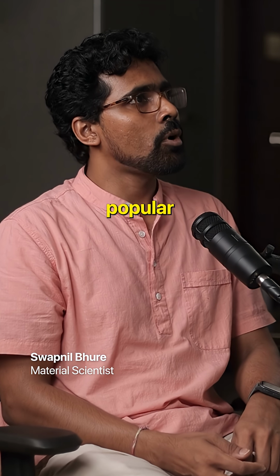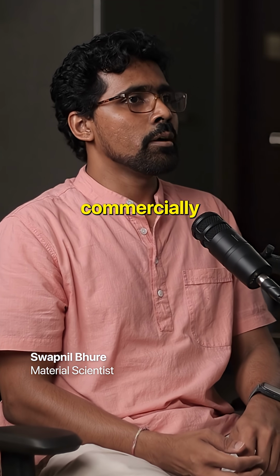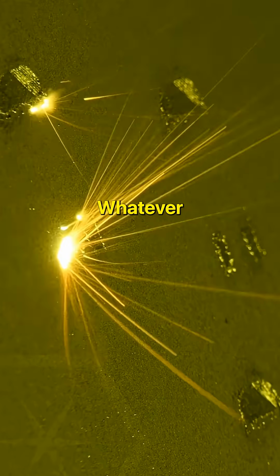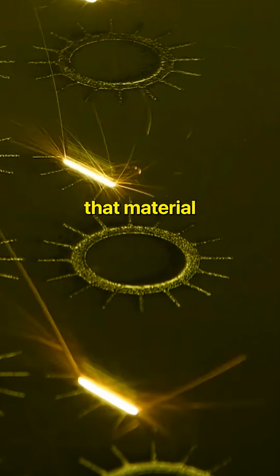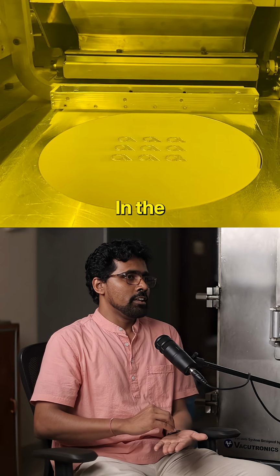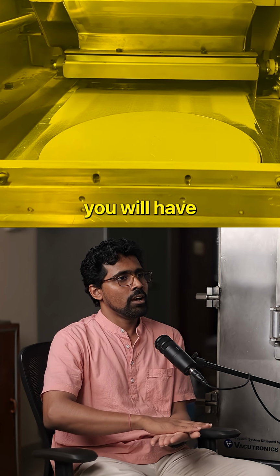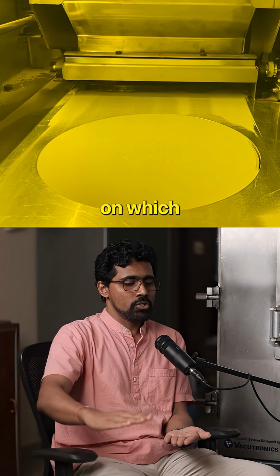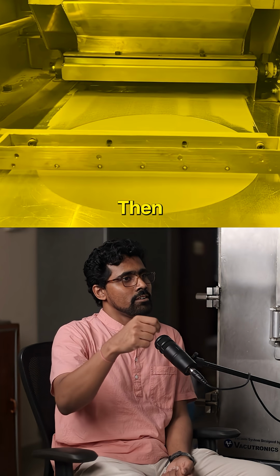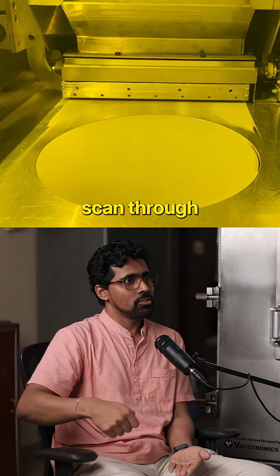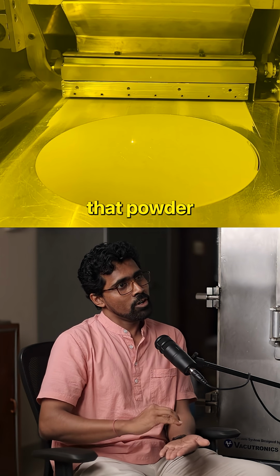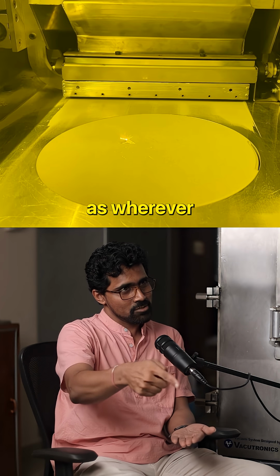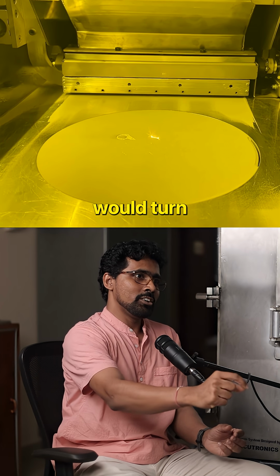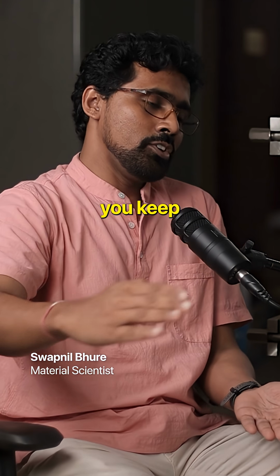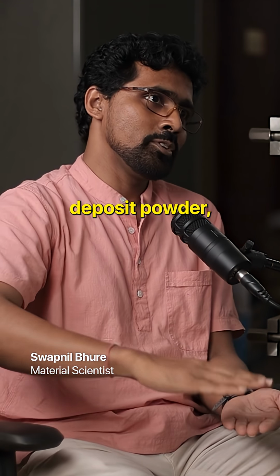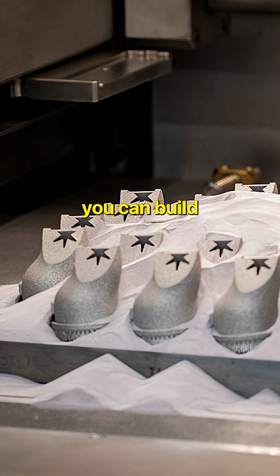I think the most popular one that is being commercially utilized is powder bed fusion. Whatever material you are printing on is called the substrate. In the powder bed, initially at the bottom you'll have a substrate, a plate or a base, on which you put a thin layer of powder. Then a laser scans through that powder and makes it fuse to the substrate. Wherever you scan the laser, the powder turns to liquid and fuses together. This way you keep depositing a layer of powder, scanning the laser, depositing powder, then scanning the laser, and so you can build a 3D structure.